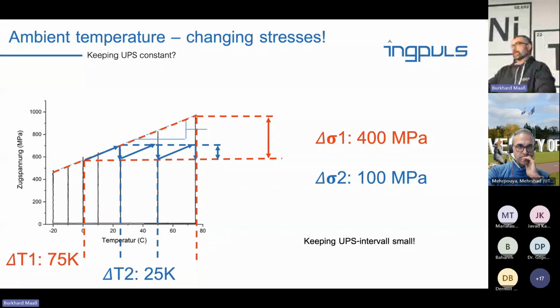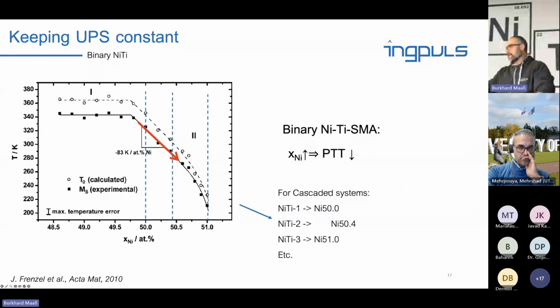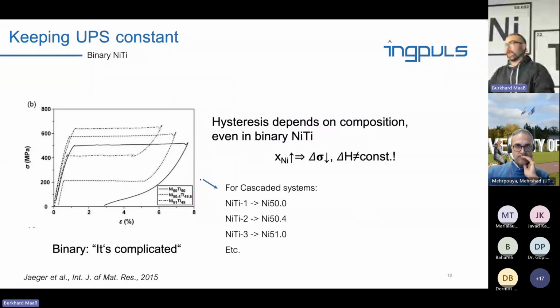And so you could, for example, for cascaded systems, buy material that starts here with a NiTi 50-50, then have a 50.4, then have a 51. Then in theory, you would have a cascaded system with different plateau stresses at different temperatures. However, in binary NiTi, the hysteresis depends a lot on composition. And if you look here and just on binary changing compositions, you do have a very different hysteresis behavior. For cascaded systems, that does not really work. What we want is the same mechanical behavior at different temperatures.